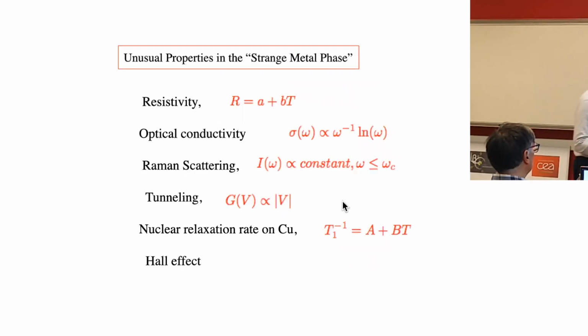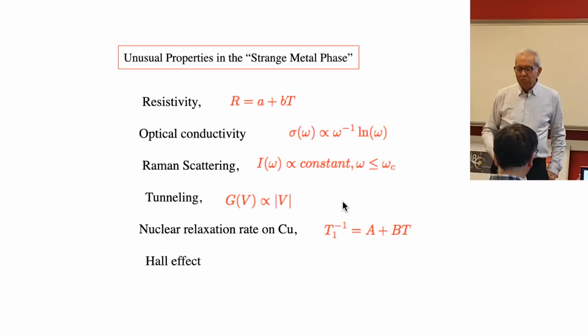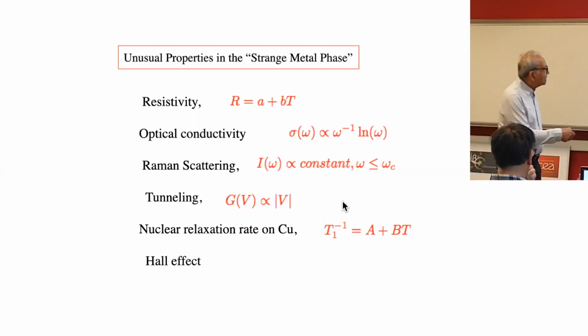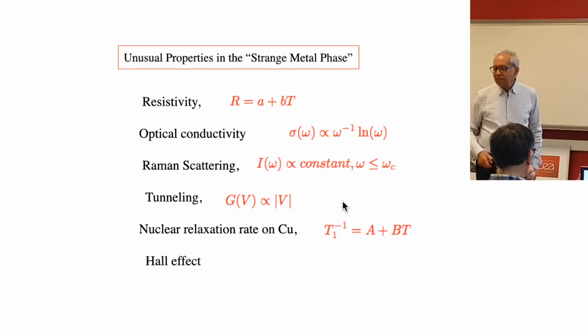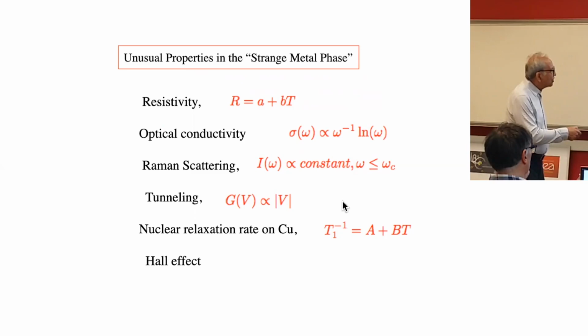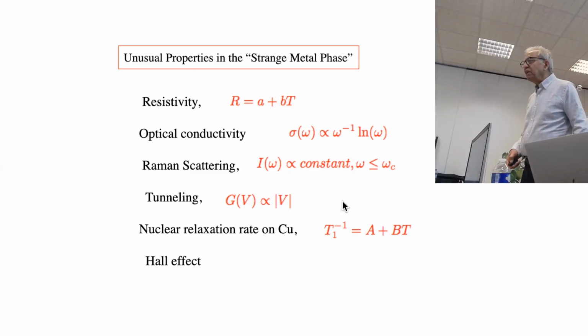Several examples here. If you measure the resistivity there, which is the most often talked about thing, there is a constant part which you can vary by varying the impurity content. There is a linear in T part, which I'll show you, and this coefficient B is within about 30% the same in all cuprate families, and this coefficient does not bear a relationship to the coefficient A. You can vary impurity content by an order of magnitude, changing A by an order of magnitude, and this does not change.